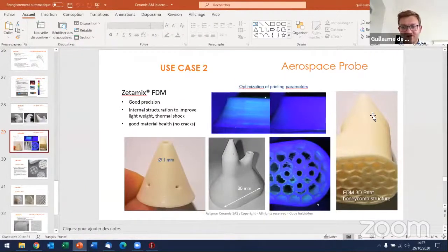Here's an example of a part that was made for aerospace. It's a very high temperature probe made to measure speed of flow. So it was a relatively big part for us. We're not used to make such big parts. But again, it was made by a customer, which is called Avignon Ceramic. And this part is supposed to go up to 1600 degrees C, and the internal channels that you can see a bit everywhere on the parts are made to measure the speed of the flow of air, basically. It's called a pitot probe.